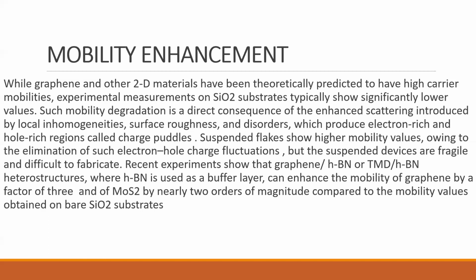and difficult to fabricate. Recent experiments show that in graphene heterostructures where hBN is used as a buffer layer, the mobility of graphene is enhanced by a factor of 3 and that of MoS2 by nearly 2 orders of magnitude compared to the mobility values obtained on bare SiO2 substrates. Scanning tunneling microscopy reveals the use of hBN reduces the charge puddles of SiO2 substrates by 2 orders of magnitude, resulting in a dramatic mobility enhancement.